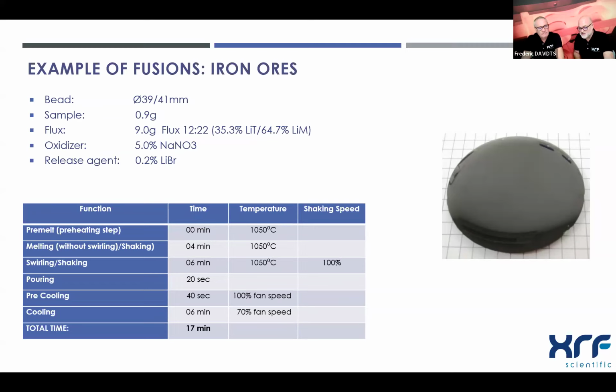We don't need to do an oxidation step in this case, because the quantity to oxidize is not big, and the fusion time is relatively fast, also 17 minutes.